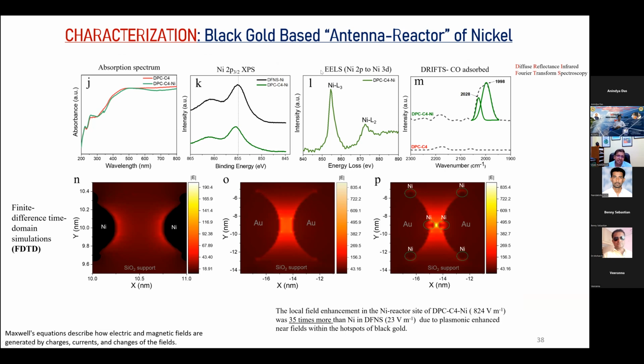If my nickel sites are really small, ultra small nanoparticles, then they will oxidize and you will always see 2+. So we carried out CO titration in a glove box in inert atmosphere using the DRIFTS experiment, and we realized that CO is chemisorbing onto the nickel, monodentate or bidentate. You get these two signals at 2026 and 1998, which clearly indicate nickel is in a 0 state, though there could be some amount of nickel 2+ as well.